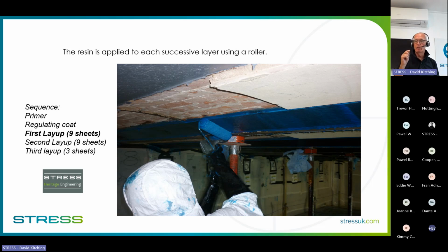And so if you don't get that bonded correctly, you might as well not bother doing the rest of it. So you want to put them up in a number of layers. Remember, it's only 0.3 of a millimeter thick, this carbon fiber sheet. So there's not a lot of weight there, even with the adhesive on it. And you do it in a layer of 9. That allows that first layer to cure properly without tending to allow gravity to pull it off.